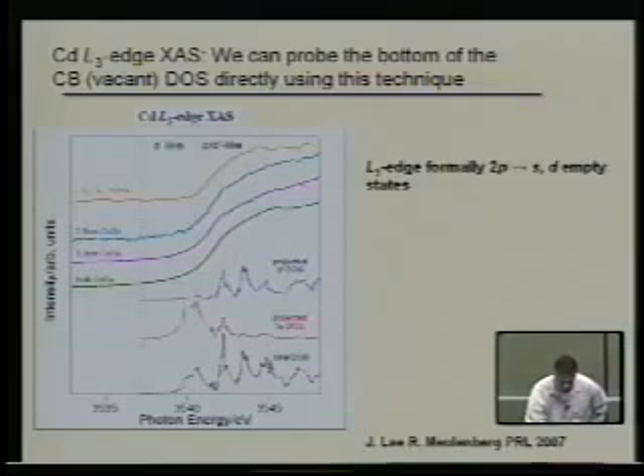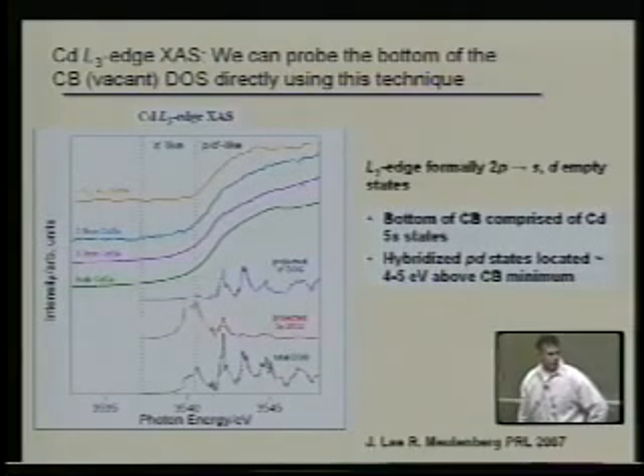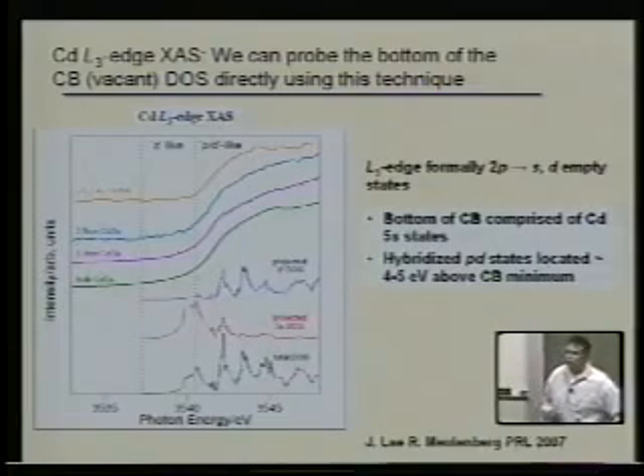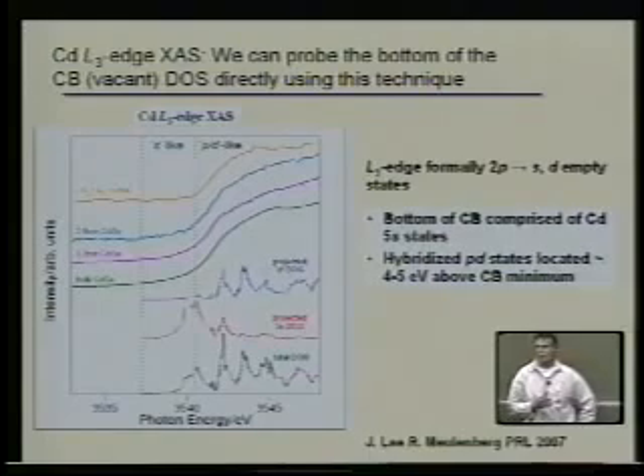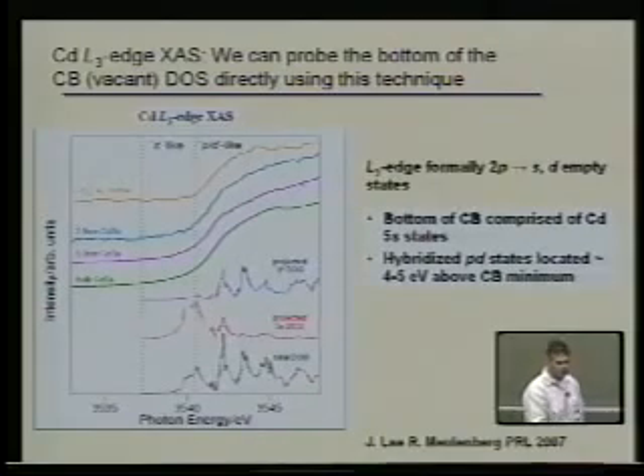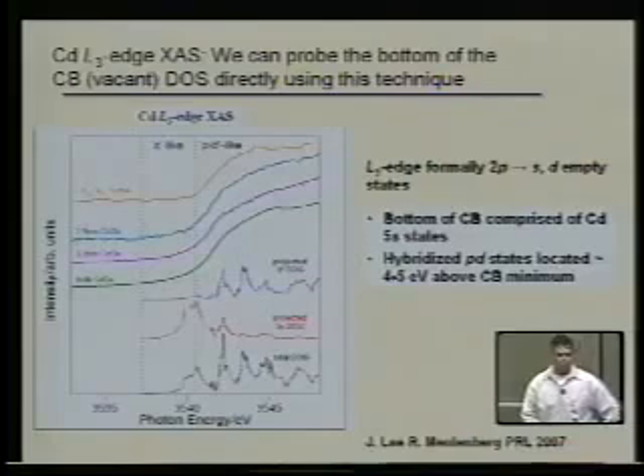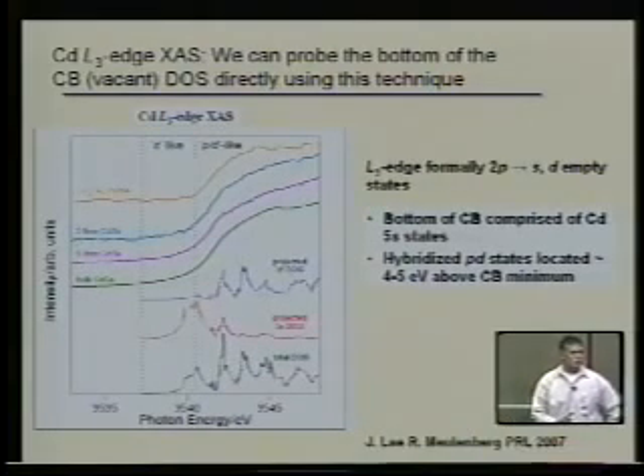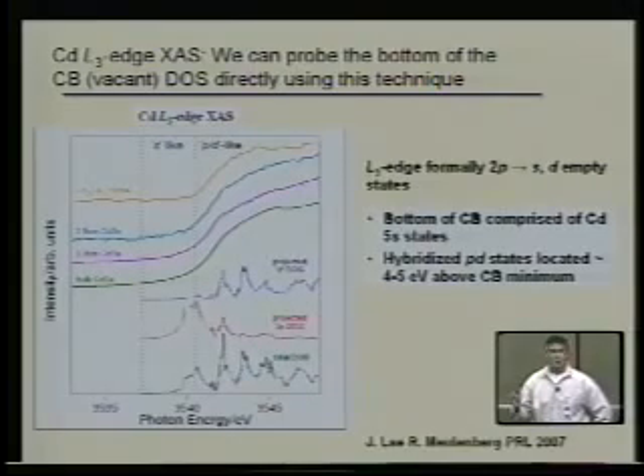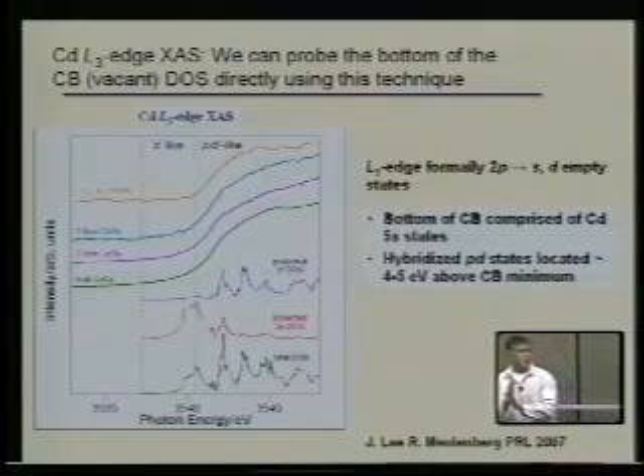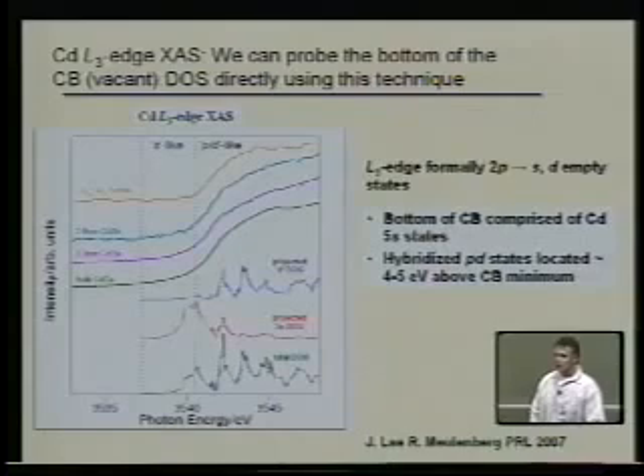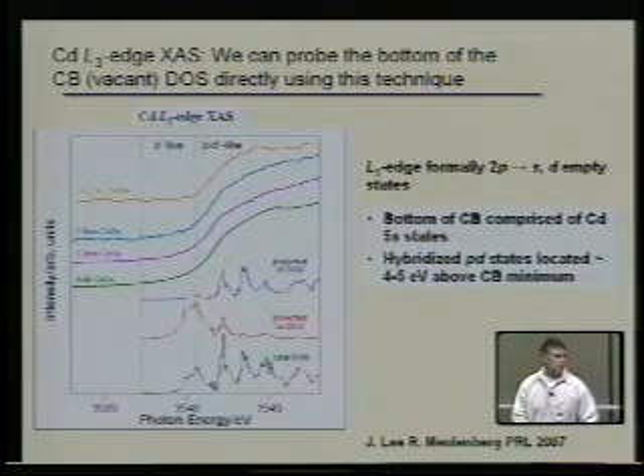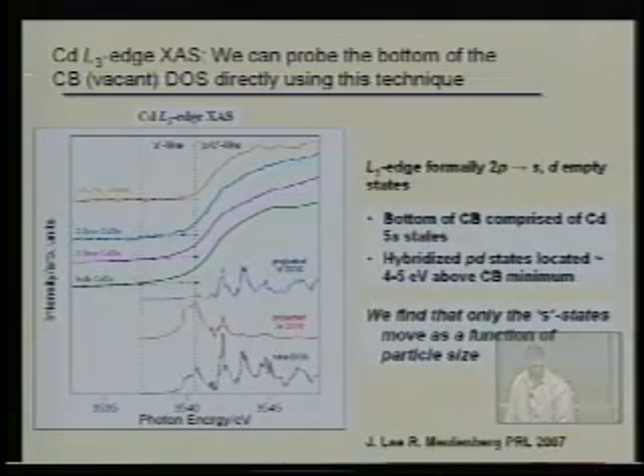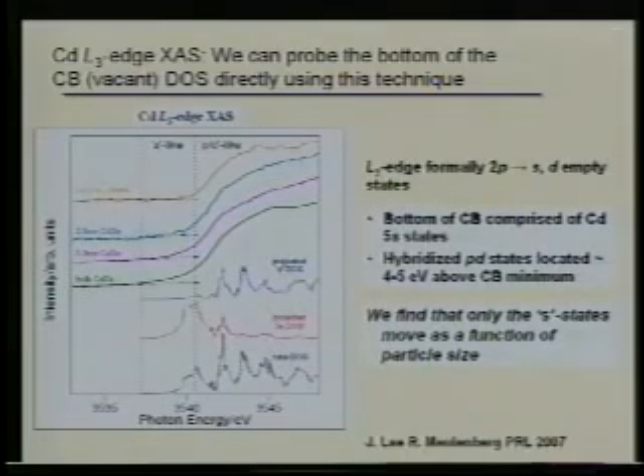So if we separate that, we find that there's actually a foot at the bottom of the conduction band that we see in our NEXAFS that actually moves as a function of size, that is associated with the S type of states in the cadmium selenide. And that's what's at the bottom of the conduction band in these nanoparticles. So we find that the S states actually move, but the PD states don't move. So this is actually quite interesting: as you increase in particle size, the conduction band is shifting, and then it comes to a value and doesn't shift anymore, because now the S states have shifted up to match with the P and D states. So here, X-ray absorption is a real winner, because we can separate the partial densities of states and actually see what's happening as a function of particle size. So perhaps that makes it a little bit clearer just to see the edges.